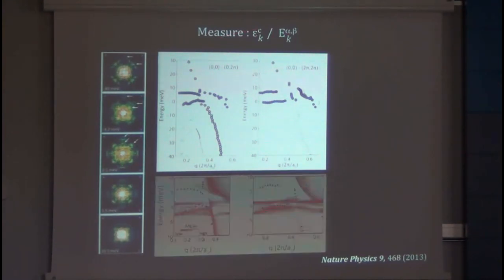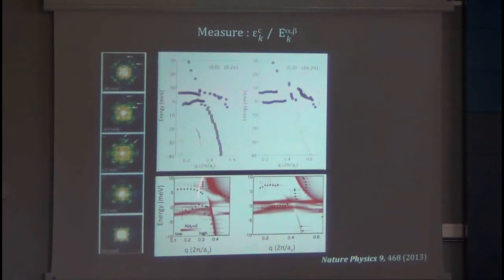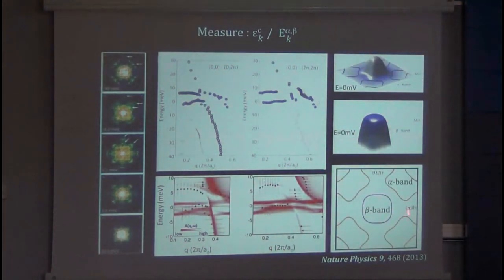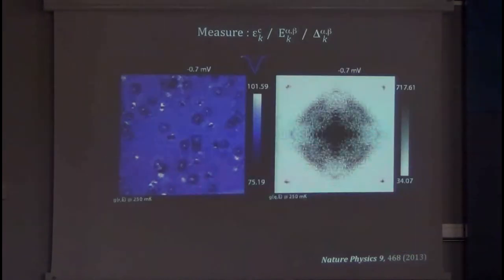Okay, so now we have enough information here to write down a Hamiltonian and parameterize a theoretical band structure and compare it with the observations. And we were able to report what the Fermi surface of cerium cobalt indium 5 looks like. It's got one band closing around the middle of the Brillouin zone, that's called the beta band. And then it's got another more complicated band, which is star shaped, square shaped, cross shaped, around the pi-pi point, this one here. And this data only became available earlier this year. So now we know the heavy band structure. That's enough information to help us search for the superconductivity.